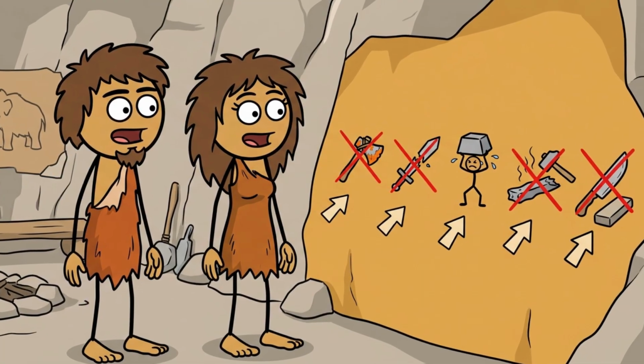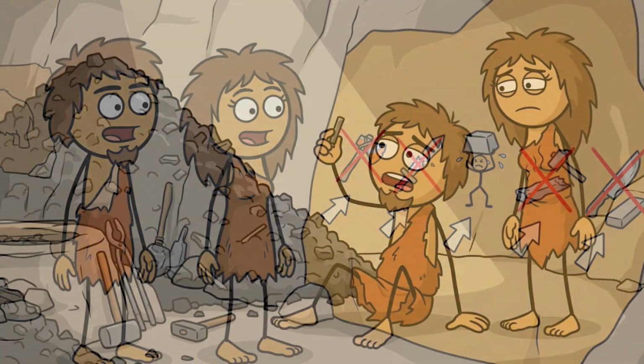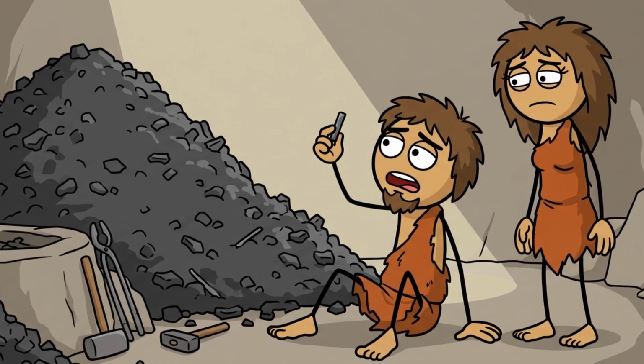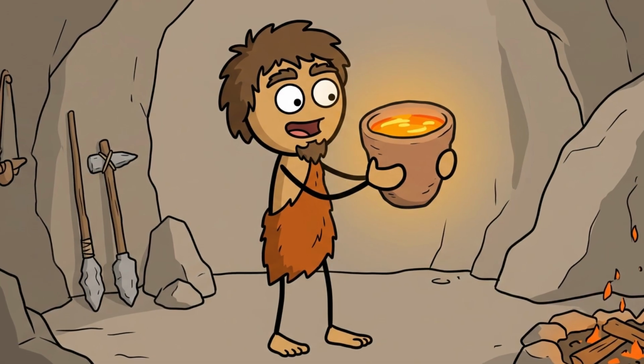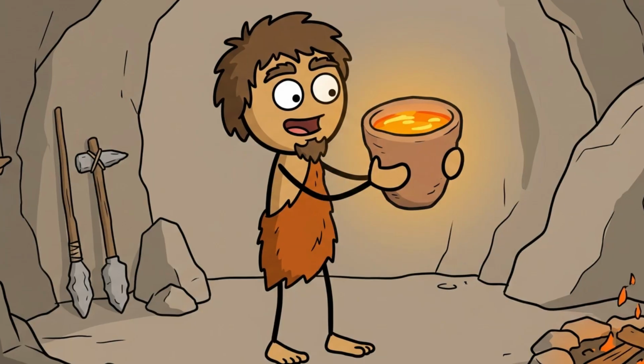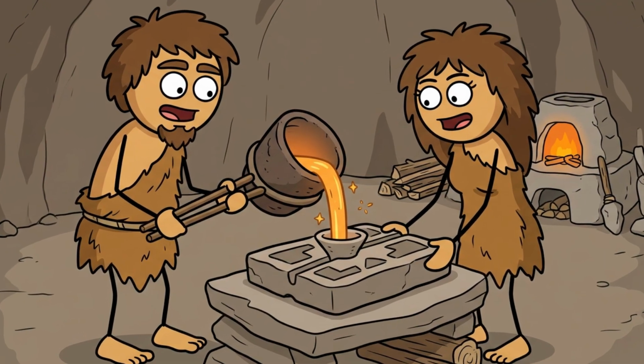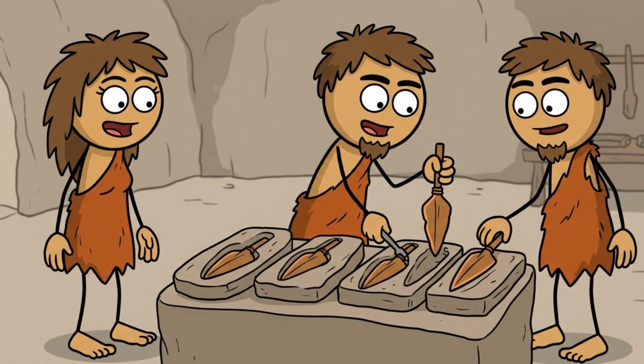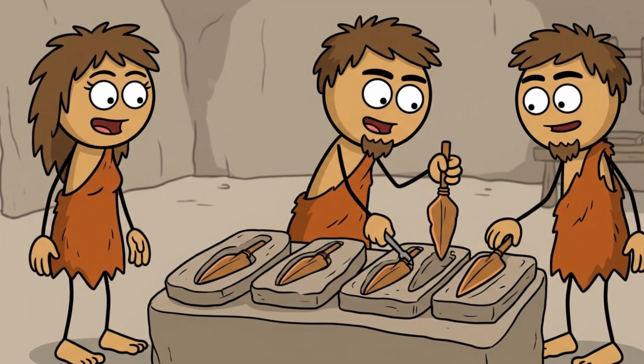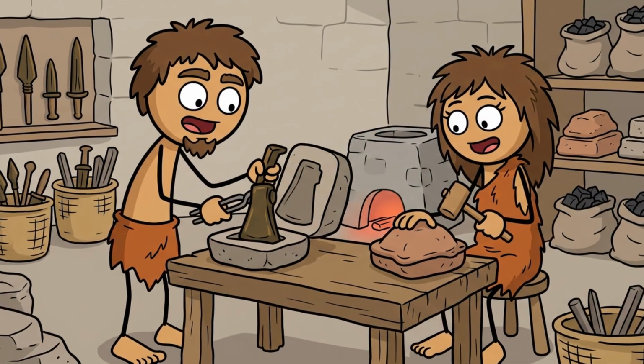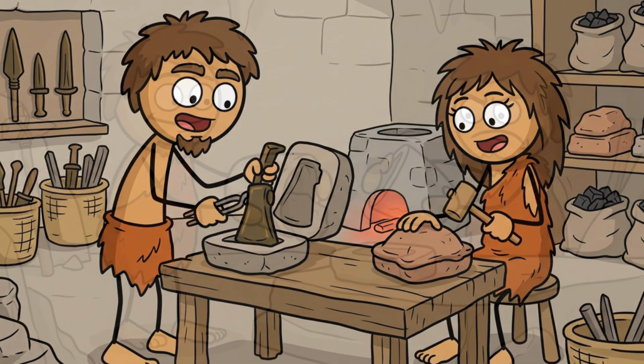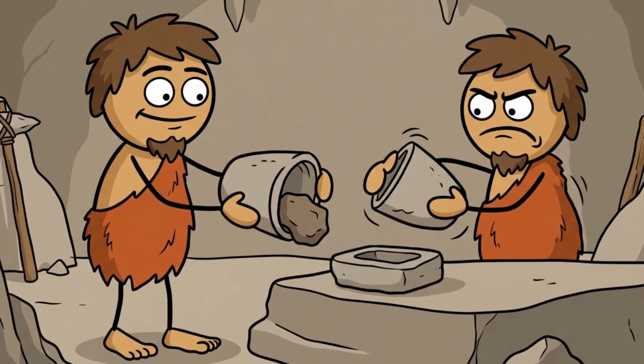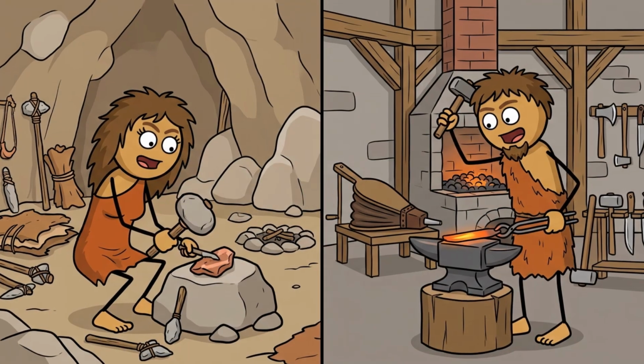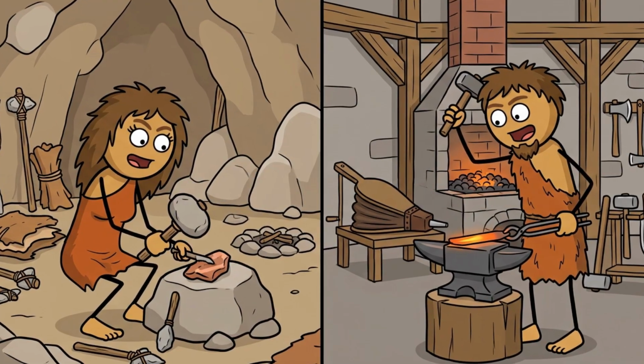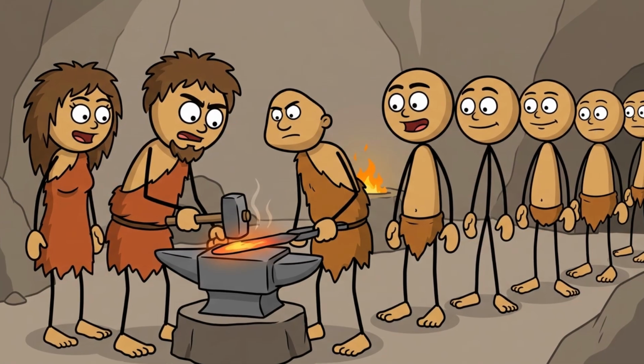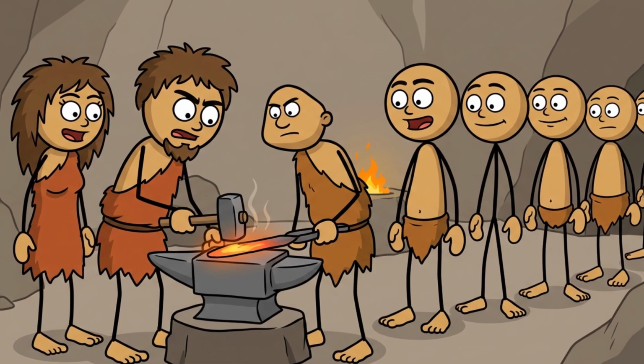Properly worked tin bronze comes in at 150 to 200, sometimes higher. A bronze sword holds an edge better. It casts into a mold, so you can pour 100 identical blades. It does not corrode into orange flakes when it rains. Bronze is, by almost every measure that mattered to a person in the year 1500 before the Common Era, the superior material. Iron is harder to make, needs more fuel, requires vastly more hammering, cannot be cast, and rusts. And bronze had something iron could not touch for another 2,000 years.